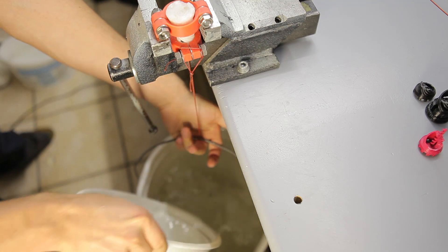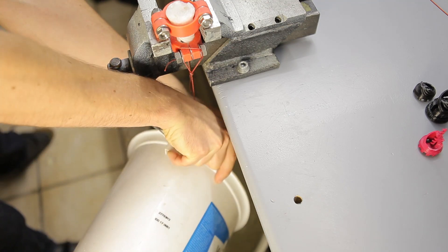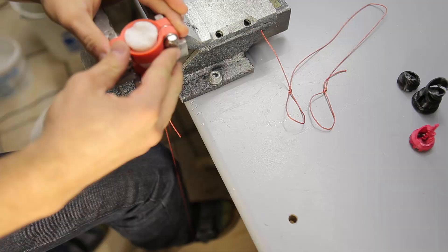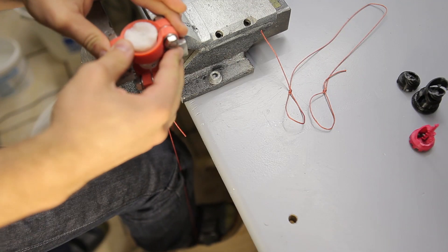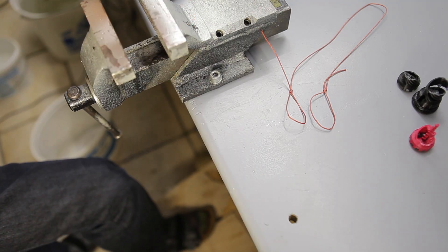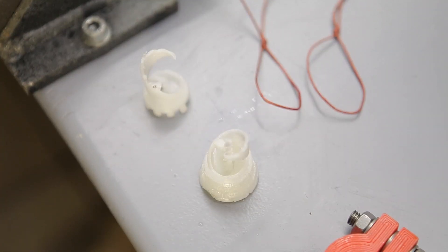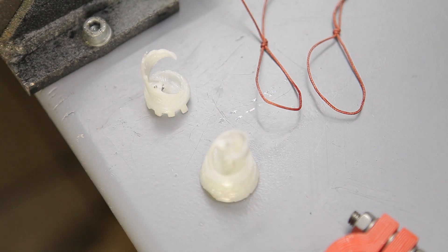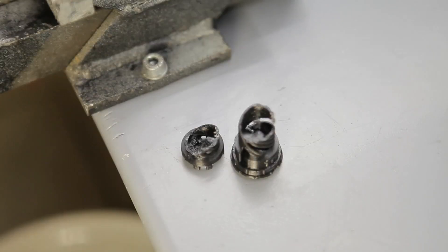Next up is the nylon bridge printed part, and that thing was amazingly strong. Not only did it survive the bucket and the bucket dropped, but it also survived my weight almost completely, I'd say 40 to 50 kilograms, and even then it didn't snap off, but tore off like a piece of cloth.